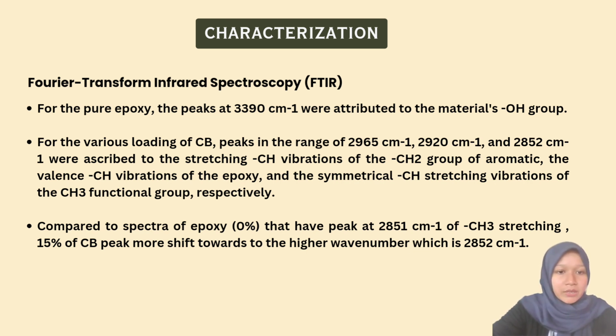For the various loadings of carbon black, peaks in the range of 2965, 2920, and 2852 cm-1 were ascribed to the stretching CH vibration of the CH2 group of aromatic, the valence CH vibration of the epoxy, and the symmetrical CH stretching vibration of the CH3 functional group respectively. Compared to the spectra of epoxy, which is carbon black 0%, that has a peak at 2851 cm-1, CH3 stretching, 15% of carbon black peak shifts toward the higher wave number, which is 2852 cm-1.